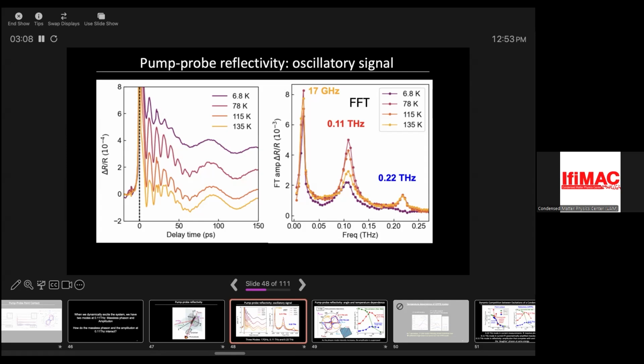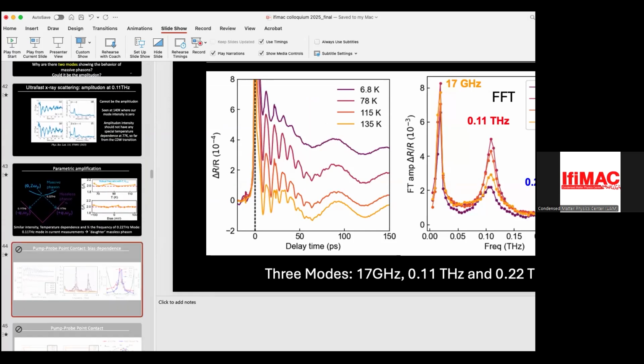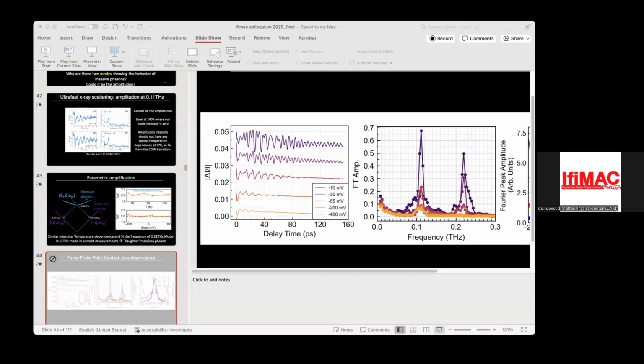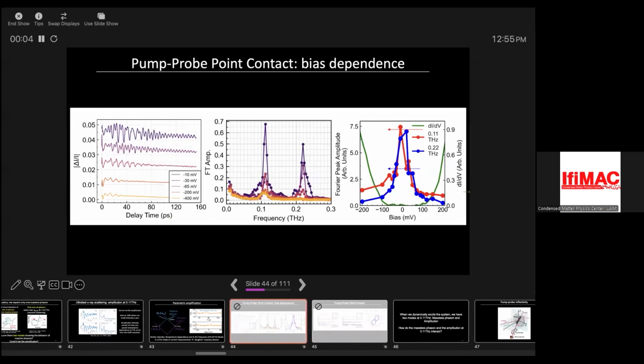But in the point contact, do these curves depend on the bias? Yes. So this is an insulator, and so I'll show you what it looks like as a function of bias. So this is the gap. But remember what this is. What I'm showing you here is the intensity divided by the current. It's delta I over I, because our signal strength depends on the current. So that delta I over I has a peak inside the gap.